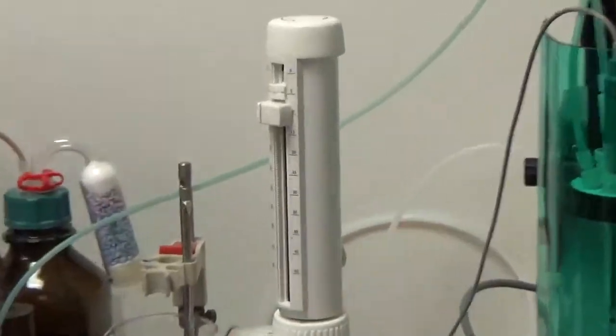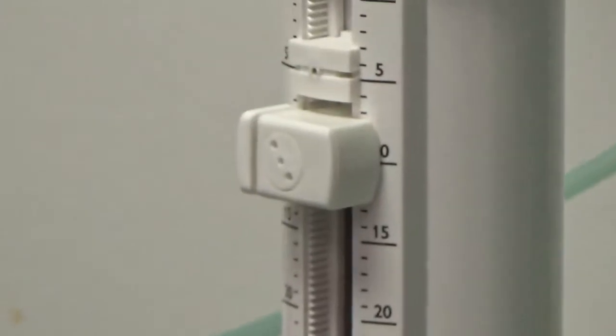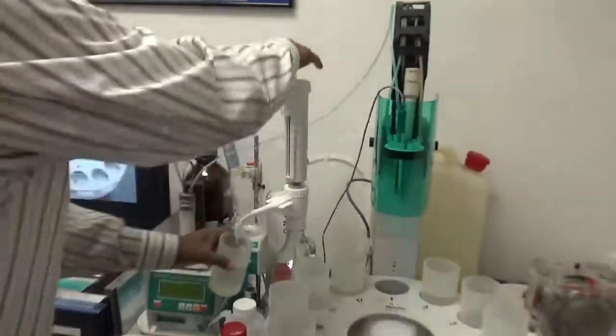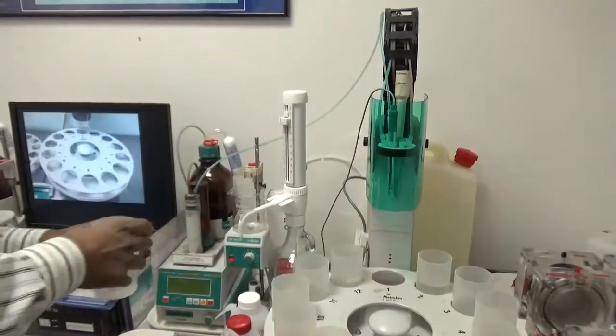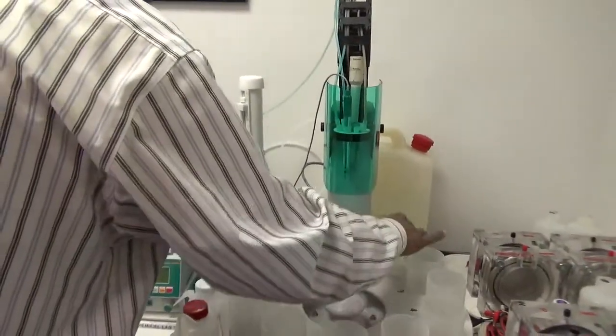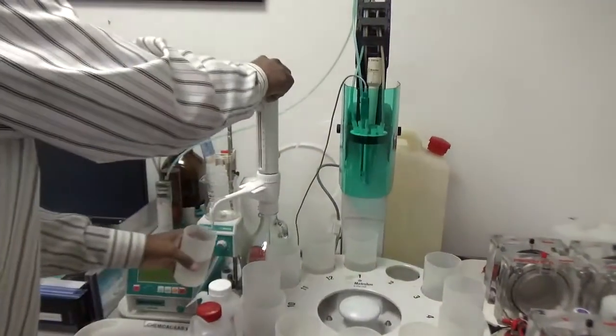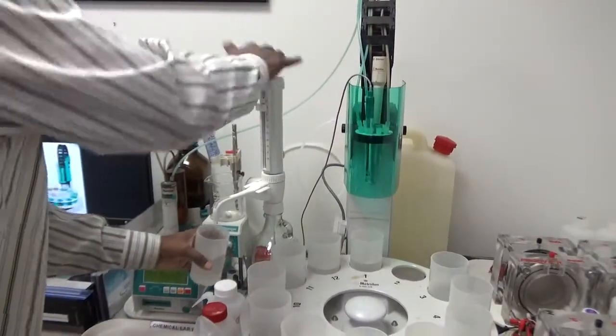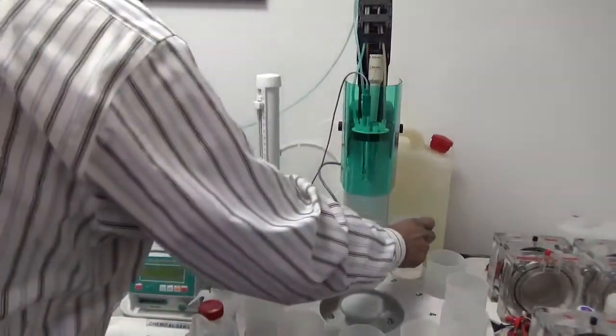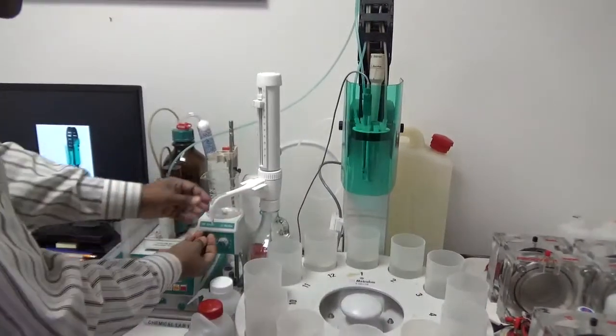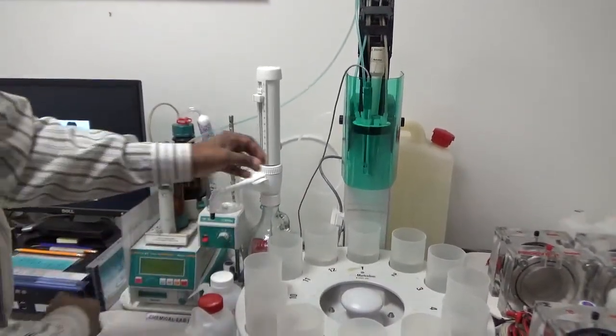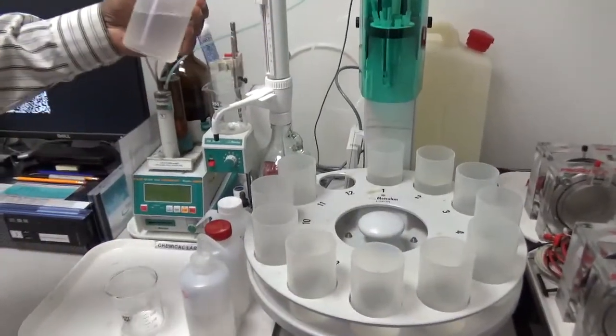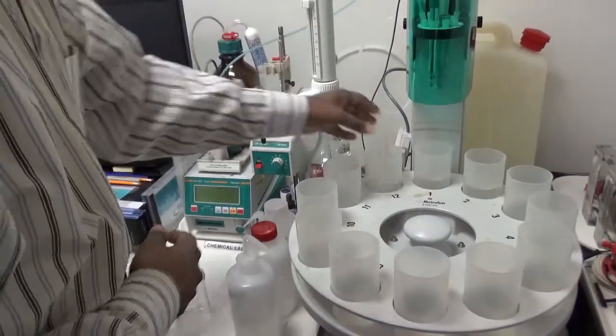We take 5 milliliters of that 0.05 normal sodium chloride. We just add 5 milliliters with this burette. We have two samples of blank, so we add 5 milliliters of 0.05 normal sodium chloride in both samples. And then station number 12 is just distilled water for cleaning the electrode.